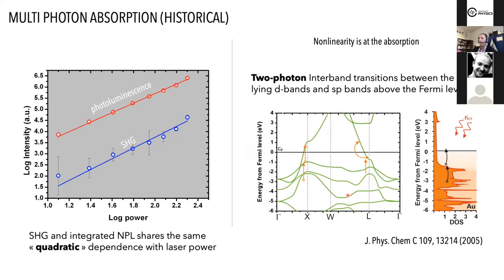laser. And so if you do this, I'm representing here in linear scale, but this is a log of the intensity versus a log of the power. And if you integrate all your signals coming from this photoluminescence spectrum I showed you before, and you put this on the photodetector, and you increase the laser power, you will see that this photoluminescence generally follows a quadratic dependence, okay? Pretty much like the second harmonic generation, which is a second order effect, and also shows a quadratic dependence to laser power.